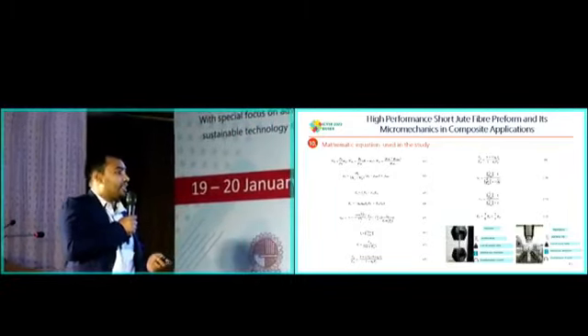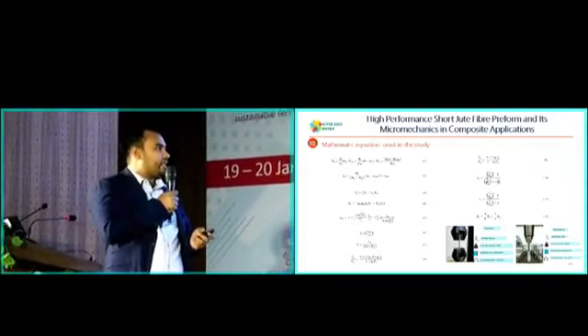We particularly conducted the tensile test and the bending test, which is known as flexural properties, to obtain the physical and tensile properties, based on the standards ASTM D638 for tensile and ASTM D790 for bending properties.